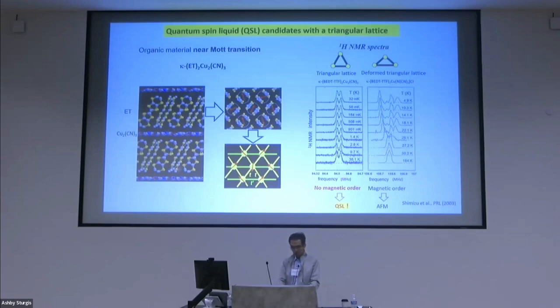This is a layered structure of this material, and the physics is going on in two-dimensional molecular layers, and this molecular layer can be modeled as an anisotropic triangular lattice with a half-filled band. The anisotropy of the triangular lattice can be varied by changing the anion layers. When the triangular lattice is strongly deformed, the system shows antiferromagnetic order, as you see in a clear splitting line. However, near the regular lattice system, this material does not show any line splitting down to 32 millikelvins.